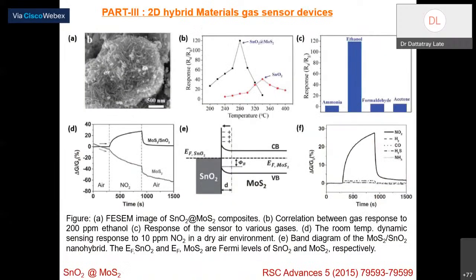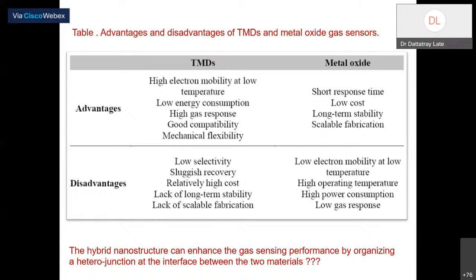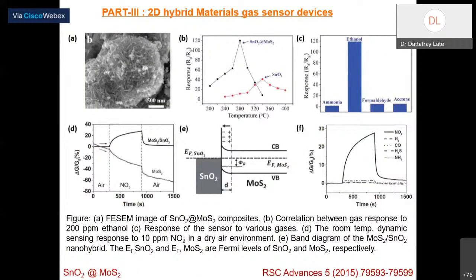So what I did here: can we make hybrid materials based on this transition metal dichalcogenide and metal oxide, where you can have the properties of these two materials? What we have done here is an experiment by hydrothermal synthesis. This is a few layers of MoS2, and we have put SnO2 nanoparticles on it. By a simple hydrothermal experiment, we have done the gas sensing performance. You can see here the response with just SnO2 nanoparticles and the response with SnO2 on MoS2.